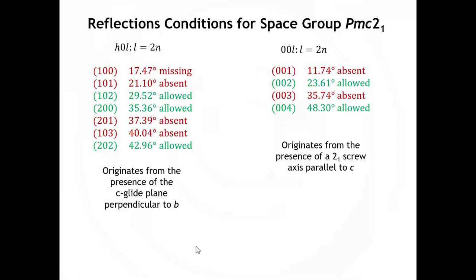Now, that means some peaks must be missing. Given the unit cell parameters, we could calculate where all of the peaks up to about 50 degrees would be located for these two classes of reflections. And indeed, the 101, the 201, and the 103 are three different HKL reflection indices where K is zero and in all cases L is an odd number — and we don't see those.